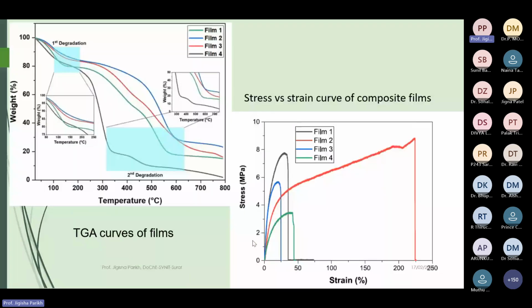So here TGA also has been performed. So this gives us the thermal stability of the films, that up to what temperature it will not degrade. Okay, so that has been identified for all the films. Okay, so initial moisture removal is there, and then up to this particular temperature there is no degradation, and then there is a degradation, and here this provides the comparison between all those films. Similarly, tensile strength has been measured for all these films, and as I told earlier, film 2, that is the major lignin part, possesses a very high tensile strength. So wherever that type of durability is required, we can utilize that film 2.